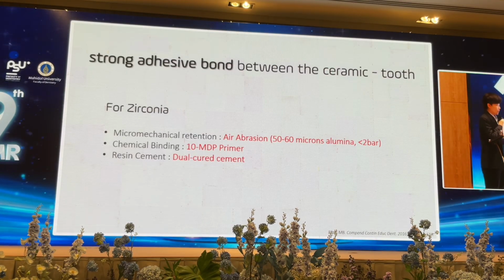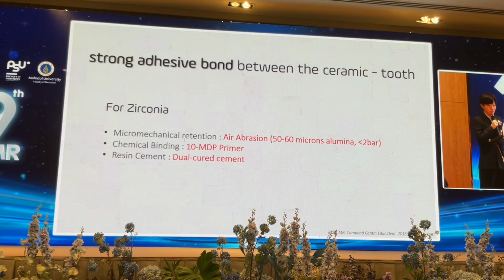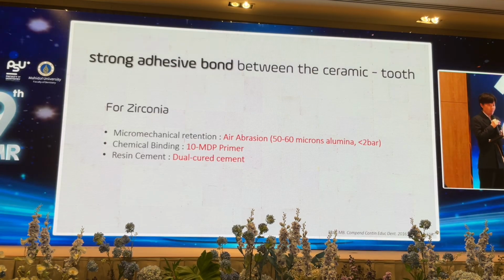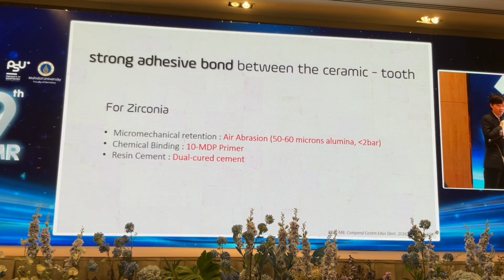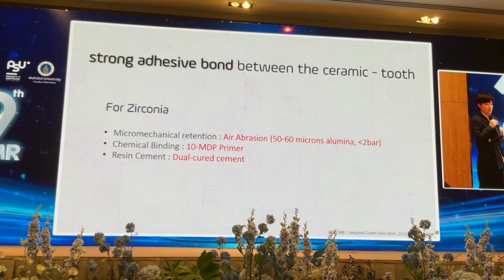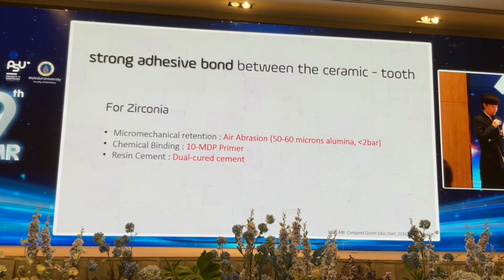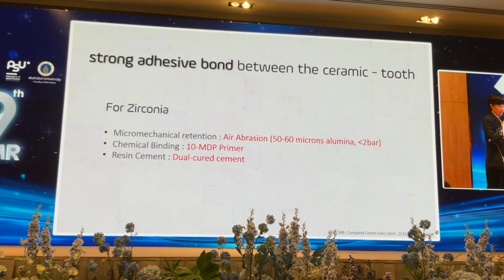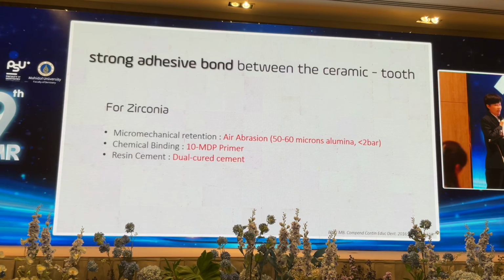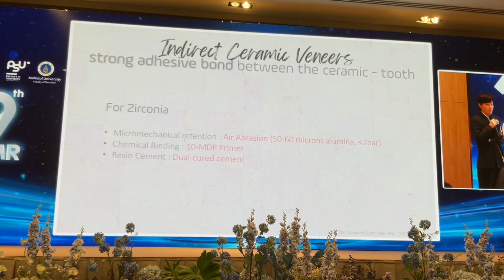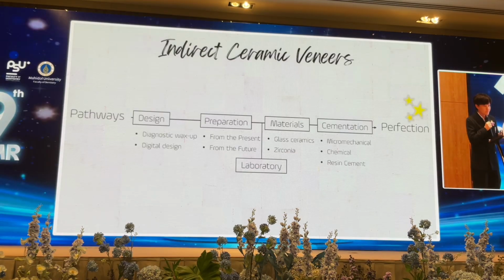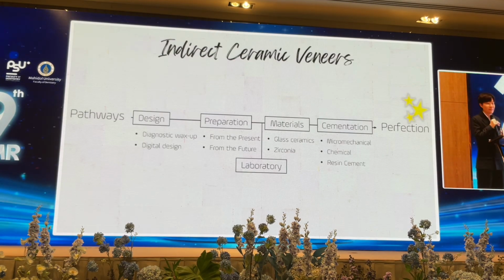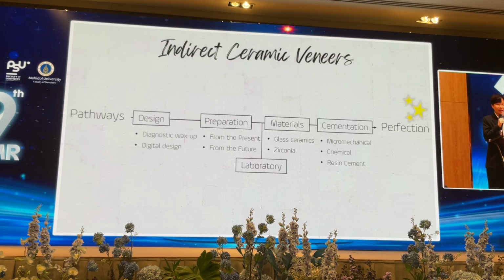for the one that contains 10-MDP, and it should be from the same manufacturer as your resin cement. And finally, choose a dual cure resin cement because zirconia is more opaque than glass ceramic. The light might not penetrate enough. And this is the complete pathway to perfection from design to cementation.